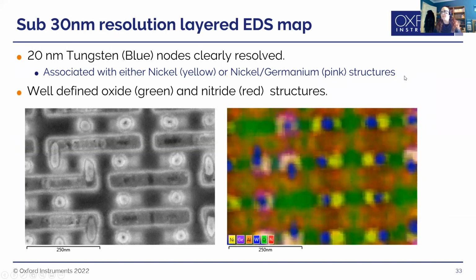So here we have a layered EDS map, and you can see a lot of the resolution and how we've got these nodes that are really well highlighted, and you can see where the oxide and the nitride structures are within this.